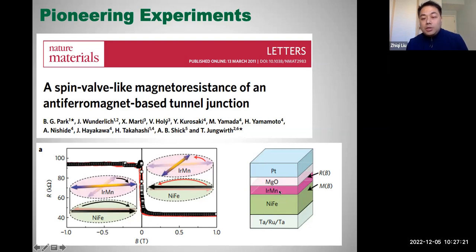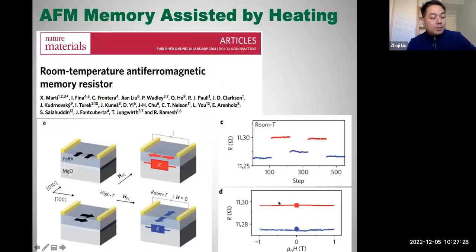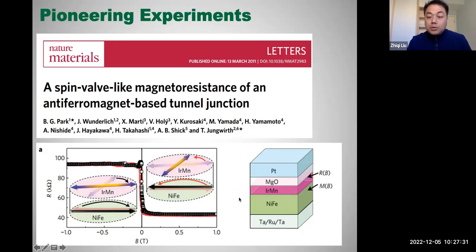What they did is they tried to use the exchange spring interaction between an antiferromagnet and a ferromagnet. They used the external magnetic field to rotate the spins of the ferromagnetic layer, this nickel iron. Then, because of the exchange spring, the antiferromagnetic spin axis in iridium manganese is also slightly changed. As a result, the tunneling resistance has a significant change at low temperatures. But unfortunately, these devices could not work at room temperature because of the very weak exchange coupling.